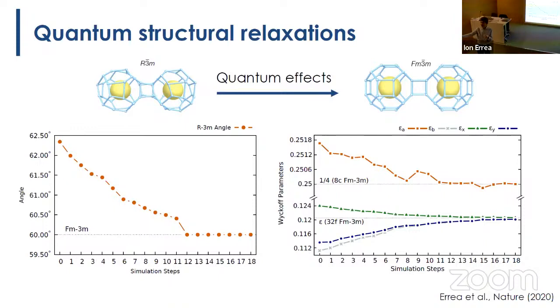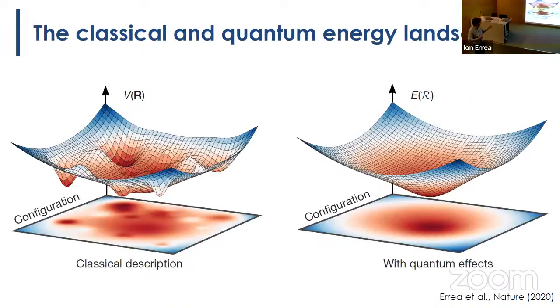We also started from a completely different structure, one of the others predicted by classical crystal structure prediction, and we also ended up in this crystal structure. So what does this mean? Classically, you have several local minima with several different structures, but when you go to this quantum energy landscape, all these minima are washed out, and you have just one minimum, which belongs to the high symmetry phase. So these quantum anharmonic effects have a huge impact on the structure.